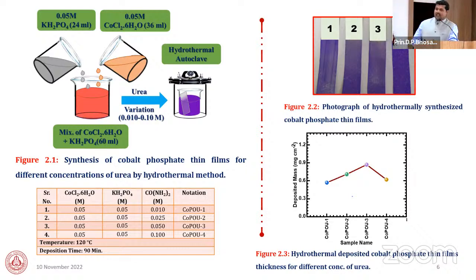In this project, the cobalt and phosphate precursor concentrations are the same, but the urea is varied. After 90 minutes, violet colored cobalt phosphate films are formed. These are the films after 90 minutes of deposition. The interesting thing is that with the increase in urea concentration, the thickness of the thin films increases up to the third sample and then decreases again because of the increasing growth rate of cobalt phosphate by urea hydrolysis. And this is the peeling of the material in the last sample. That's why the thickness of this film is reduced.